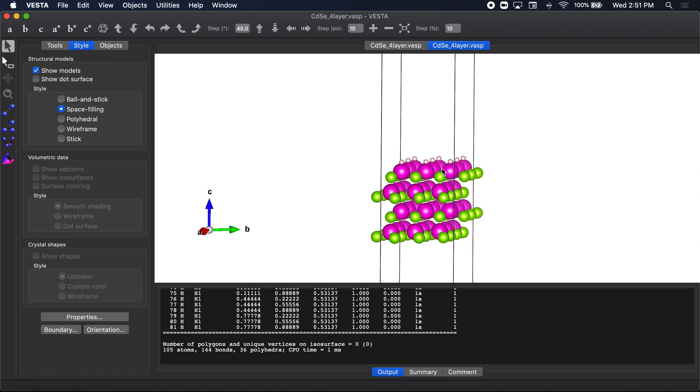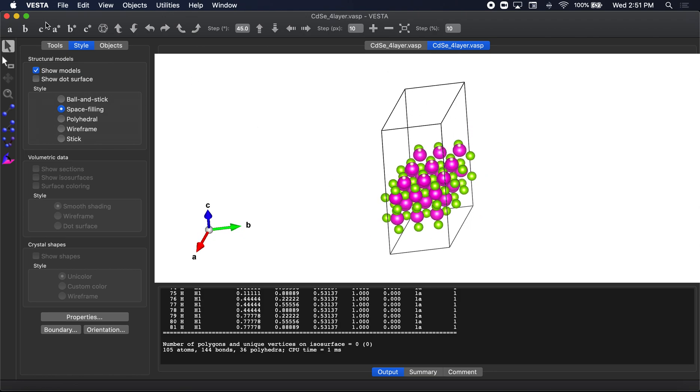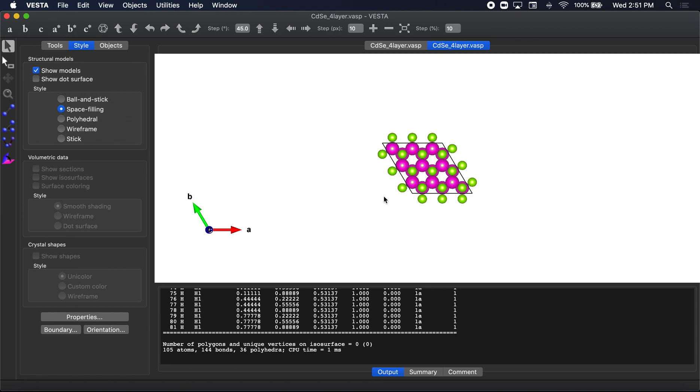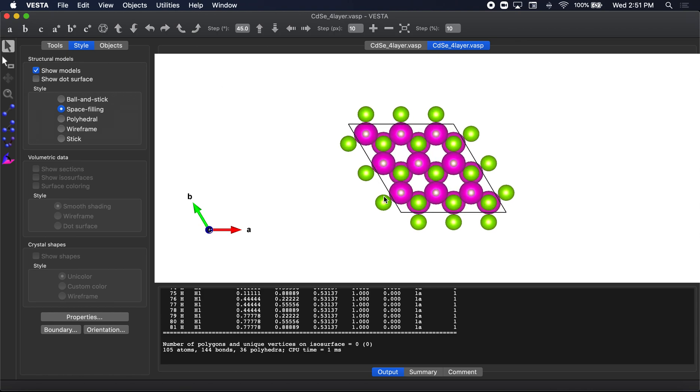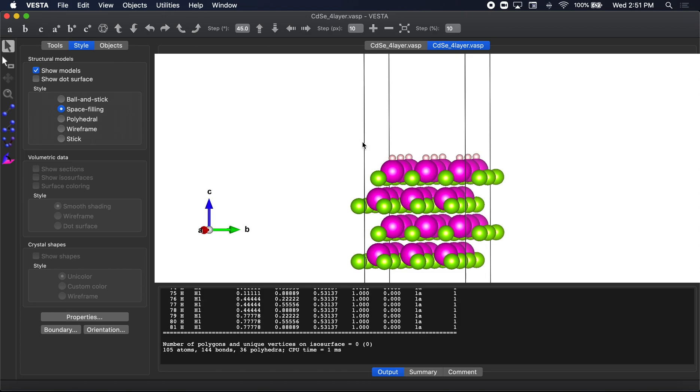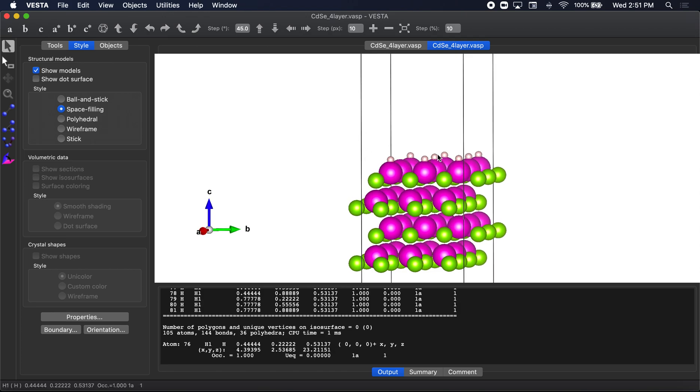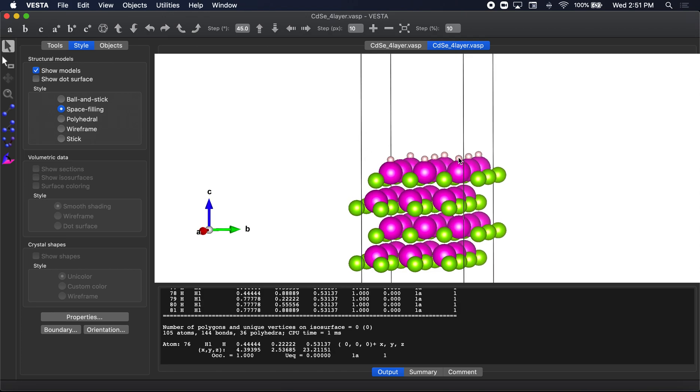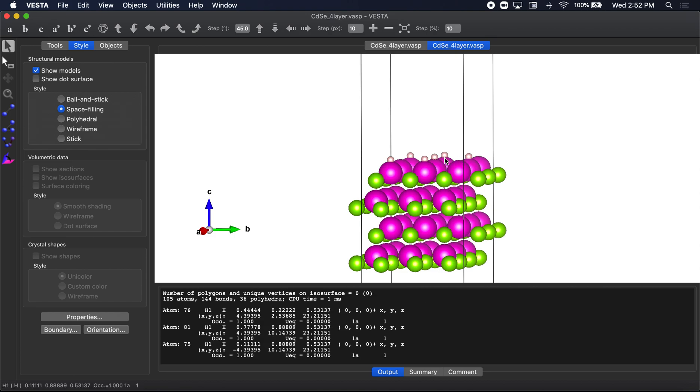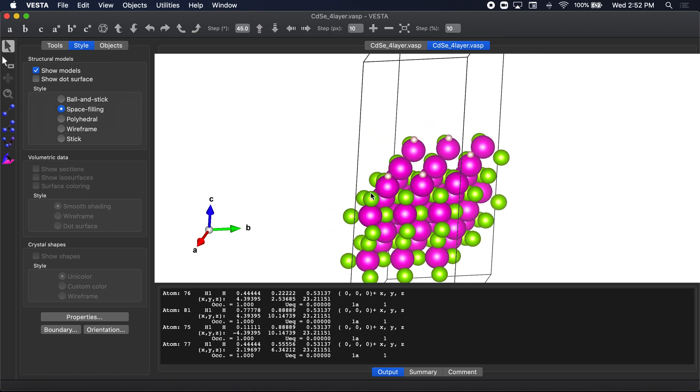So, but anyways, the reason why you want to have a larger surface like this is because when you passivate a surface with hydrogen, it's often the case that actually not all of these surface sites are passivated. So if you wanted to, there's a certain passivation density. So if only 50 percent of the surface was passivated, what you would do is you would basically delete half of these atoms. Okay. So you could manually come in now and delete half of these atoms. You know, the actual atoms you're going to delete, that's up to you.